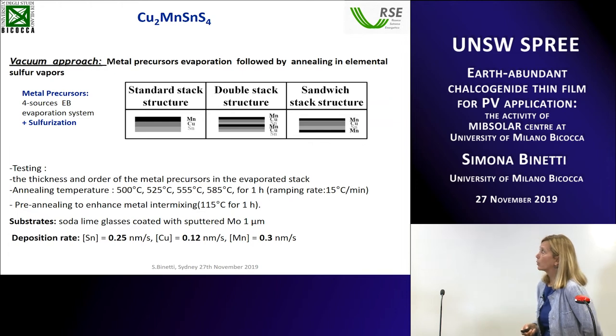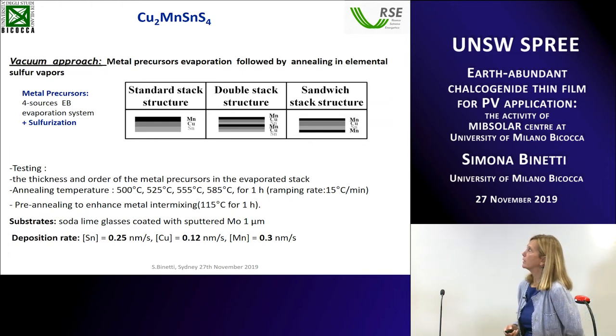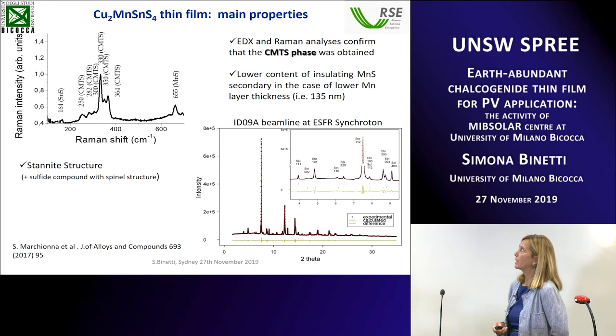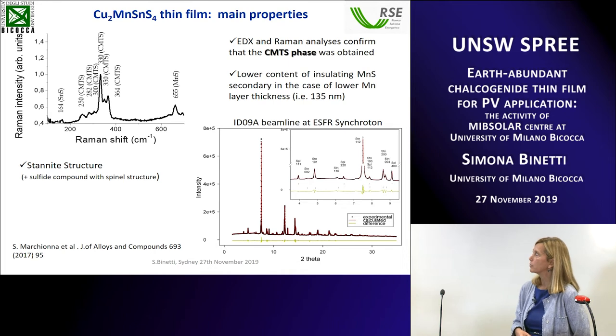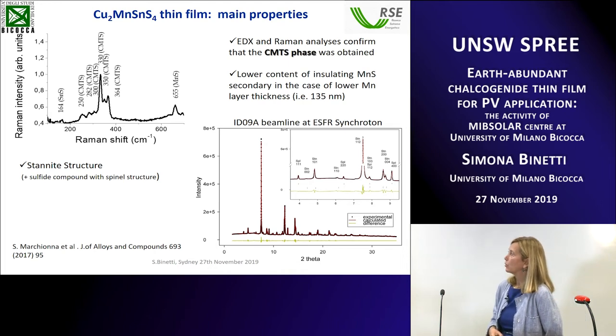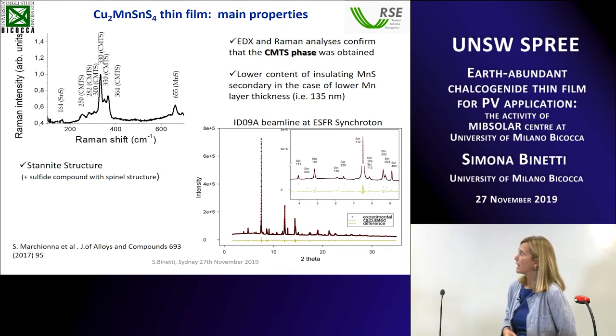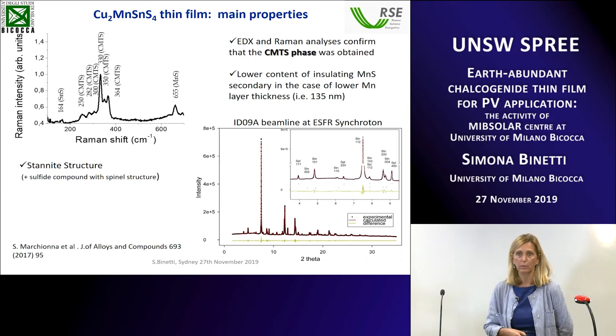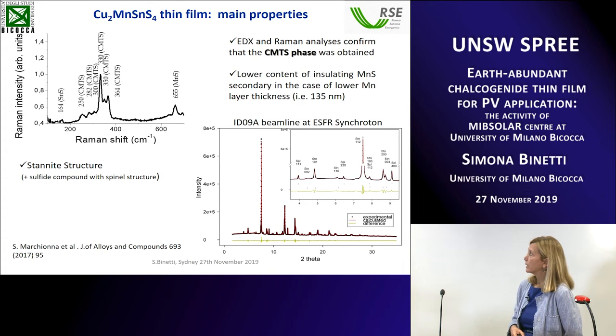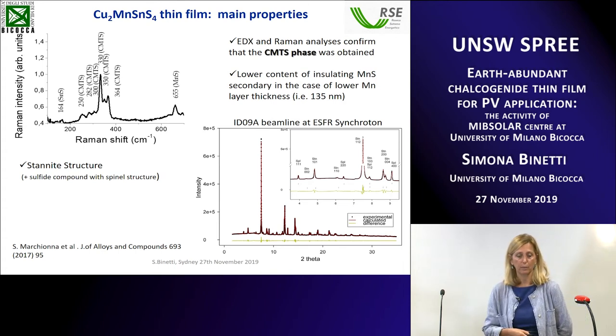We checked the quality of our material. We have seen that according to EDX and Raman analysis, we have the CMTS phases. Of course, we have some secondary phases, mainly manganese sulfide, that can be detected also by Raman spectroscopy. And according to X-ray diffraction analysis, we have a stannite structure instead of the Kesterite one, as expected. And this has been proved also by performing X-ray diffraction analysis